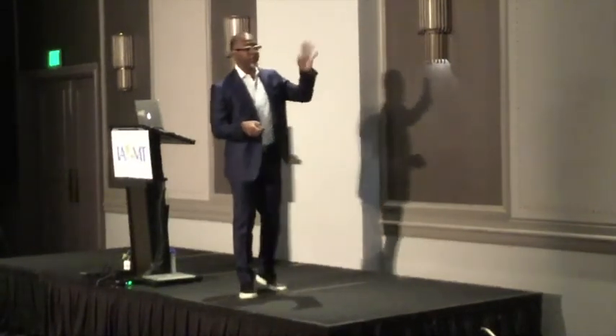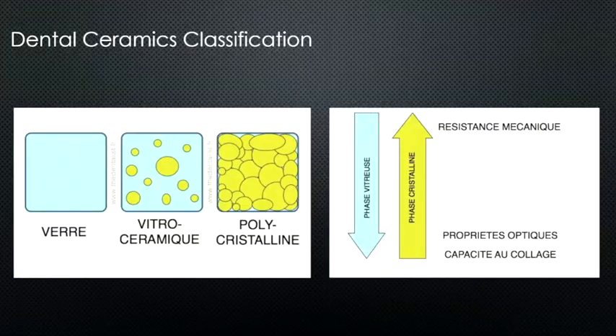Now, the best slide I could find to explain this was a French one. French is my first language. So verre means glass, vitrocéramique means glass and ceramic, and this means polycrystalline. And you get a higher mechanical strength when you're on the crystalline side, and the mechanical strength drops when you go into the glassy side. That's why your windshield will fracture faster than your implant, because your windshield is glassy. Whereas the zirconia is opaque and has a greater mechanical resistance.